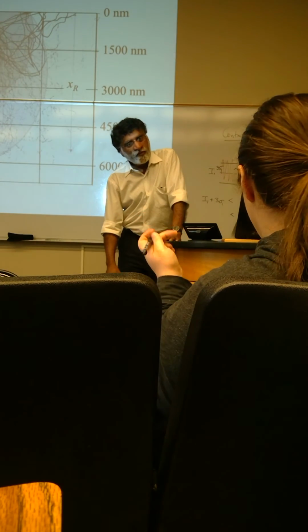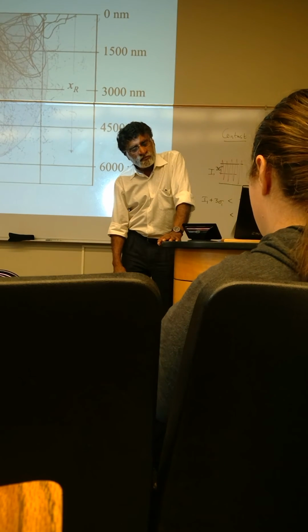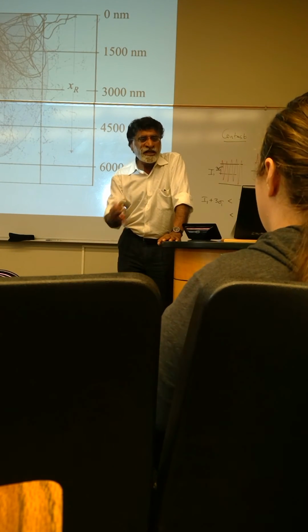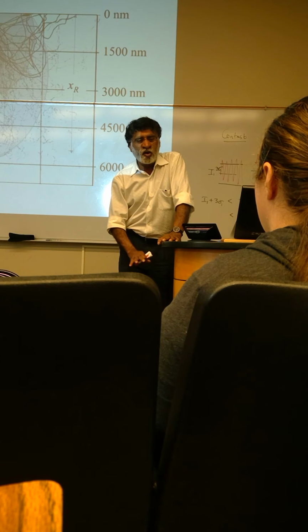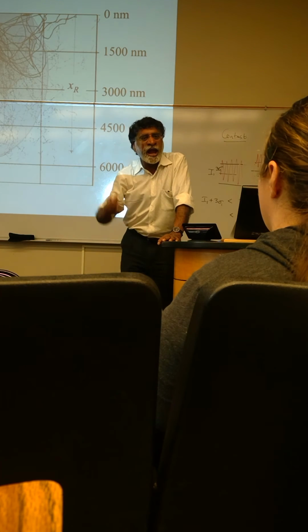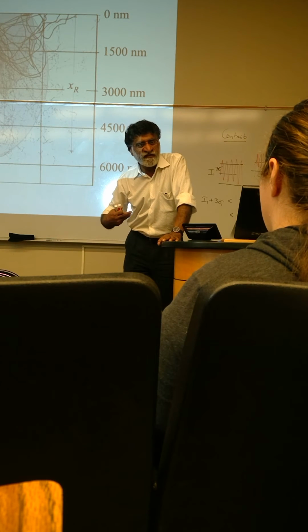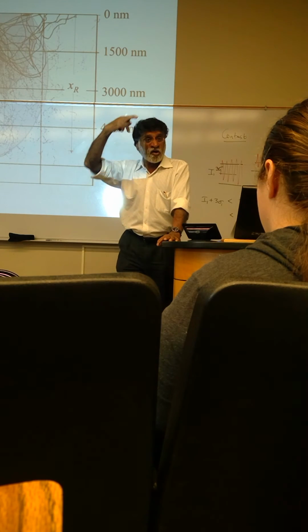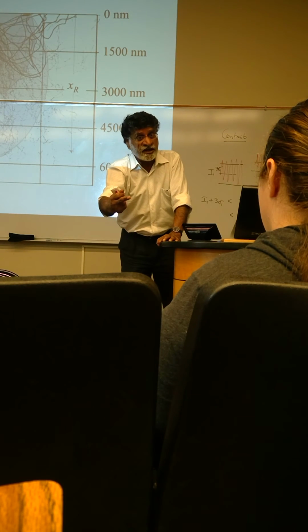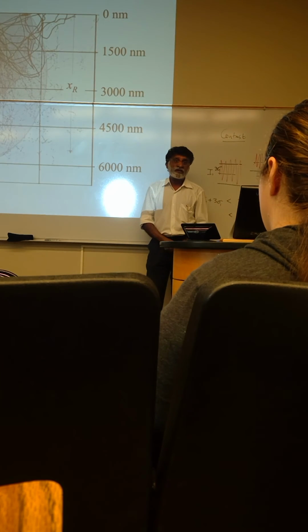So the penetration depth is then only related to the mean free path in the sample? To some extent it's related to the mean free path. No, it is both the mean free path and the energy of the incident electron and the cross sections. The cross section is related to the mean free path, but it's a cross section now of inelastic scattering. So you have to make sure that you understand which cross section you're working with.